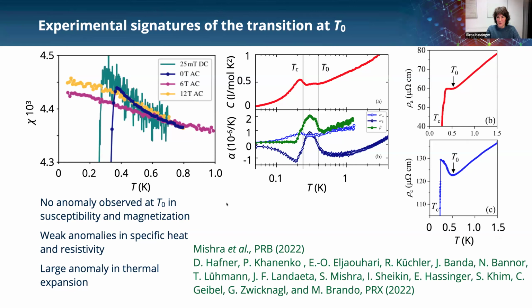And I'm going to show you what we know from bulk measurements. So here's the susceptibility as a function of temperature, measured from DC magnetization in green and from AC measurements in blue. And you can see that across the phase transition, there are no clear anomalies. So that's why we thought either this is a very weak magnetic transition or it's a non-magnetic order.